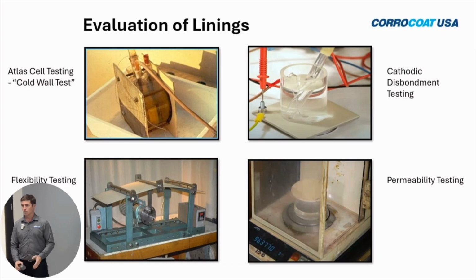Now, we don't only do that for the operating environment. Most customers will want us to do that test for the maximum operating temperature or in upset conditions. We will test it to failure in some cases because you want to know how far the coating will go. Whenever you're looking at separation vessels and process vessels, you want to know the limit because these are really, really important vessels to a process. That $100,000 tank lining is a drop in the bucket compared to the downtime for some of these things.